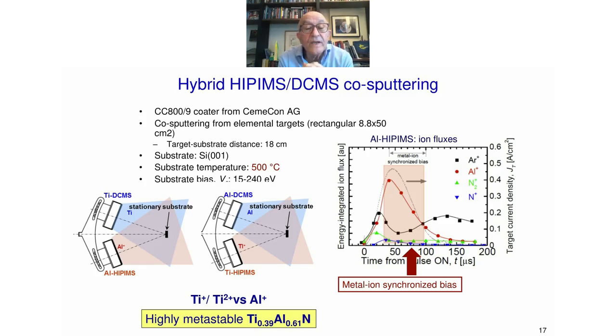Okay, now we're into the hybrid system conducted in a CemeCon equipment. Deposition temperature is 500 degrees Celsius. And here we compare titanium aluminum nitride deposited first by titanium DC plus aluminum HiPIMS. Then we change the targets and we use aluminum DC and titanium HiPIMS. So we deposit highly metastable films with 60% aluminum nitride, to gauge the ability to deposit dense films with this desirable composition. In fact, we're comparing the effect of titanium plus versus aluminum ions, and that's explained in the next slide.